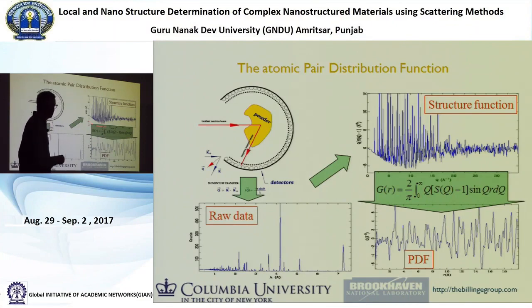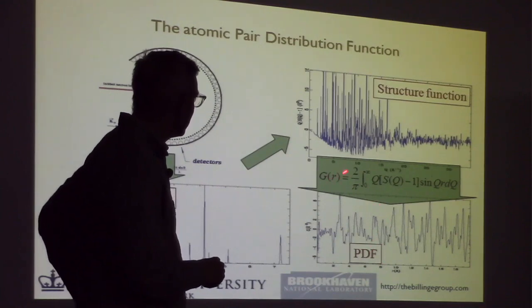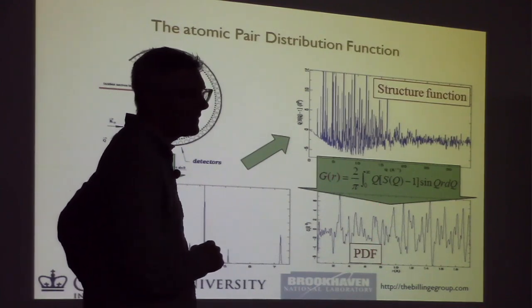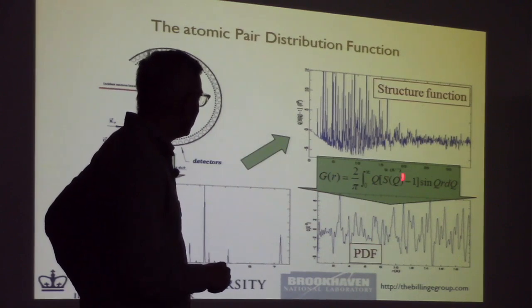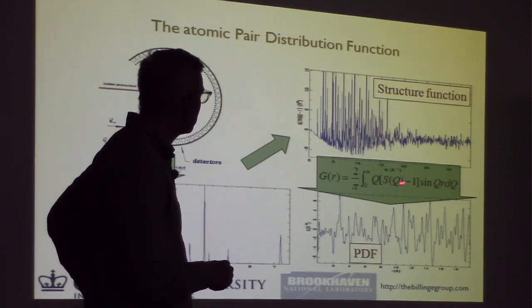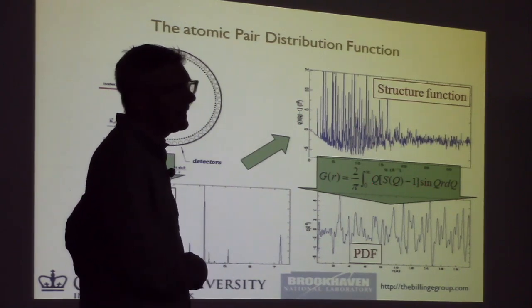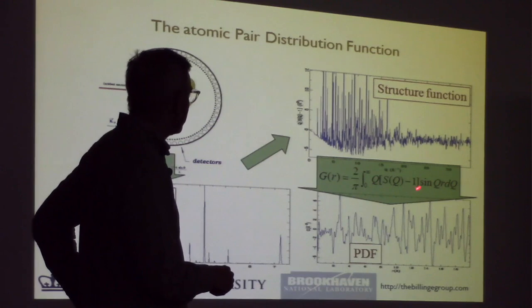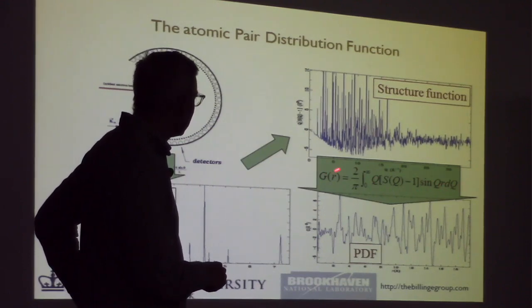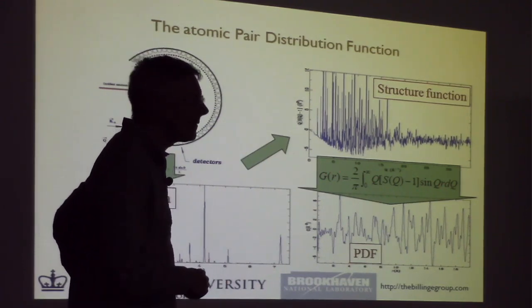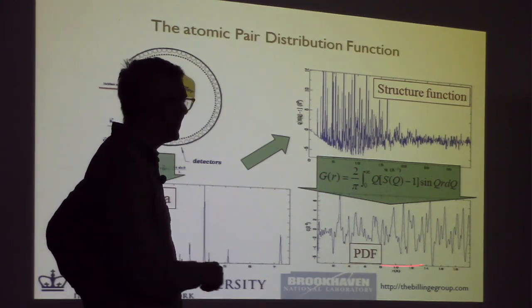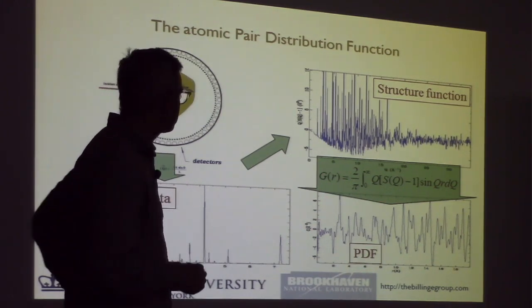What we do then is we take this complete structure function and we Fourier transform it. So we end up with this function G of R. This is the pair distribution function, and it's related to S of Q through this sine Fourier transform. So we take this, actually this is Q times S of Q minus 1. So we take S of Q, we subtract 1, multiply by Q. I'll explain later what Q is. And then we do this sine Fourier transform, and we end up with this, and this is the PDF. So it's actually straightforward to obtain this function directly from the data.